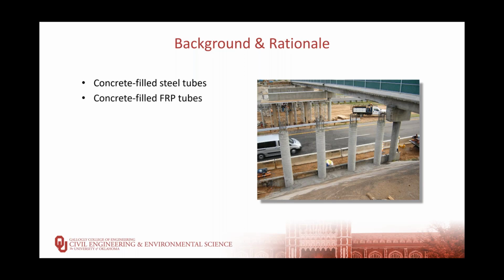To try and combat that problem, other researchers have examined fiber reinforced polymer tubes filled with concrete. The FRP tube is resistant to chlorides and other deleterious materials, but unfortunately, these columns did not have as good ductility because the FRP, of course, is a very linear elastic material up to failure as compared to steel, which has a nice plateau.